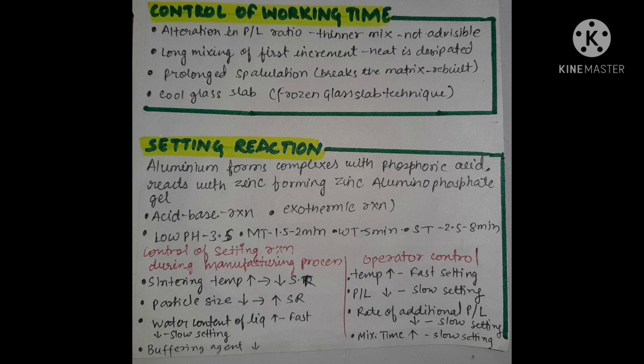Then setting reaction. Aluminium forms a complex with the phosphoric acid, reacts with zinc forming zinc aluminophosphate gel. It is an acid base reaction and exothermic reaction. The pH is 3.5. Mixing time is 1.5 to 2 minutes. Working time is 5 minutes. Setting time is 2.5 to 8 minutes.